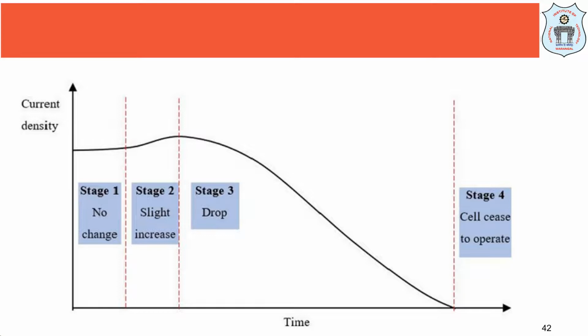Okay. So what happens? This carbon was actually thought to improve the anode conductivity and may be observed as a slight increase in the cell performance. If you look at this diagram again, in stage 2 there is a little increase in the current density because there is little deposition of carbon material taking place in the pores of the anode material. So thereby we have a little increase in the power density also. Okay. And what happens further, with further time?